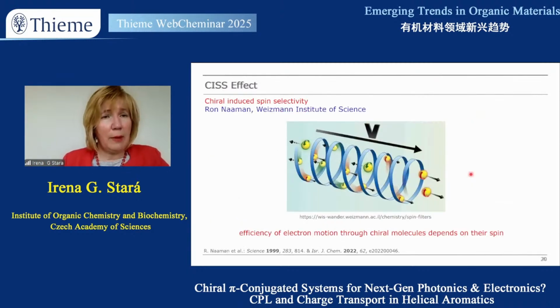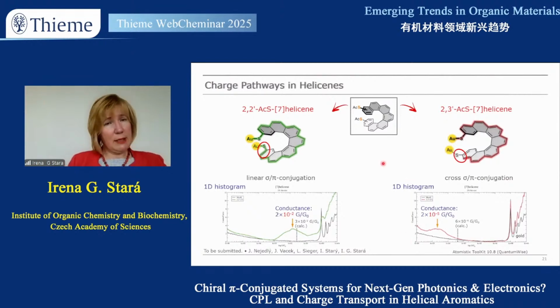Why is it important to investigate it? It's for example for the CISS effect. CISS stands for chiral induced spin selectivity, which was introduced by Ron Naaman, and it means the efficiency of electron transmission through chiral molecules depends on their spin, which is important, for example, for spintronics. So we decided to study this phenomenon on these two compounds. It's a heptahelicene, which bears two anchoring groups in different positions, 2 prime, as it is in this picture. Acetylthio groups are a little bit shifted to position 2, 3 prime, and this is shown here.